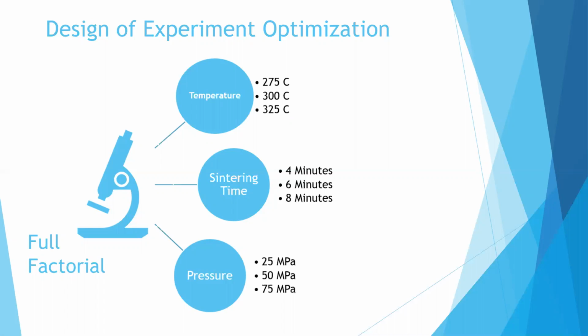The temperature will be altered in order to find the critical point for graphene oxide reduction and high temperature impact on scaffold structure. Sintering time will be altered in order to identify the impact of sintering time on graphene oxide reduction and any porosity changes in graphene welding. Finally, pressure will be altered in order to identify the impact of ambient pressure on the porosity of the structure.